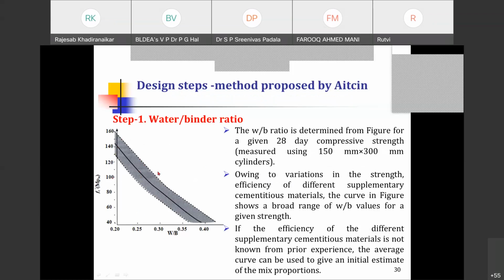This band is given. It depends on the material properties that you have selected. Based on that, for the same strength, you can vary water cement ratios. So the water binder ratio is determined from this figure for a given 28 day strength, measured on cylinder, of course. This is measured on cylinder. Why this band? Owing to variations in the strength efficiency of different supplementary cementitious materials.